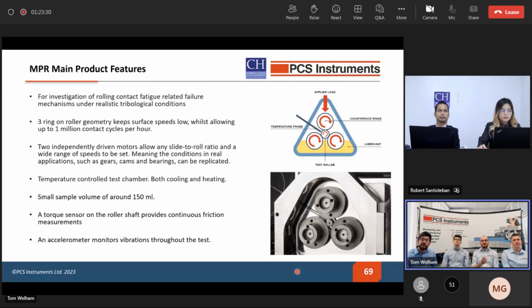So here's the main overview of the features of the MPR. It's a triple contact fatigue rig, which means that we are investigating 3 contacts in situ. We have a central roller specimen, and this is the test roller. This is the specimen which generates the damage during the test, and we have 3 counterface rings equally spaced on either side. This kind of setup allows us to test many cycles in a very short space of time. In fact, it does 1 million cycles per hour, and this allows us to test applicable design lives in a short space of time.